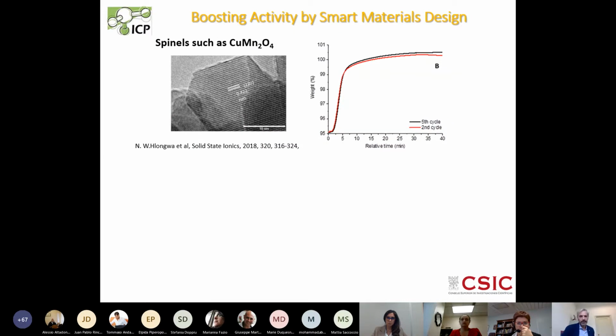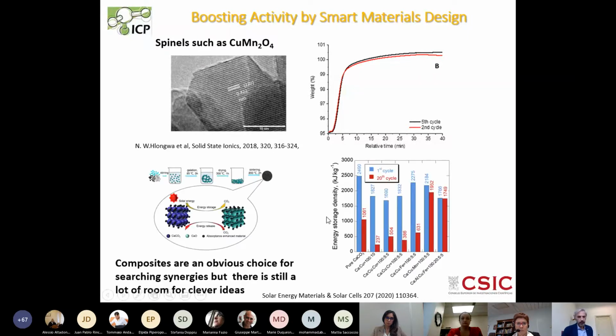Apart from the pure manganese oxide, we can use another mixed oxide like the spinel, for example, this one with copper, that is providing certain advantages in terms of the rapid rate for the recovery of oxygen, but it's not huge. I mean, this material is not perfect either, because the energy density is not great. There are also some possibilities that we are thinking about, combining these materials in composites. This has been done before, not with oxides, but with carbonates. That is also a material for thermochemical storage. So I think there is a certain field here for improving materials.